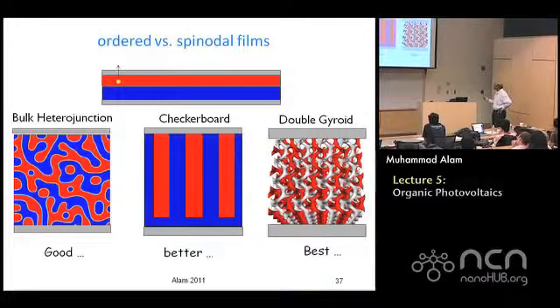And then the structure like this, which Professor Agrawal's group have also worked on, this type of double gyroid structure, is good, not because as a solar cell it can beat VOC or short circuit current or fill factor in any way, because it cannot. You can mathematically show that the VOC of these three structures will essentially be all the same. But what it does is that it traps the phase so that it cannot phase segregate. Now many times, of course, the width is not really what you need, which is too small, so it doesn't collect excitons very efficiently. That's the problem with this structure. But other than that, if you could make it, this self-trapped structure would be the best, because this is above the percolation threshold, all connected, and at the same time highly reliable.